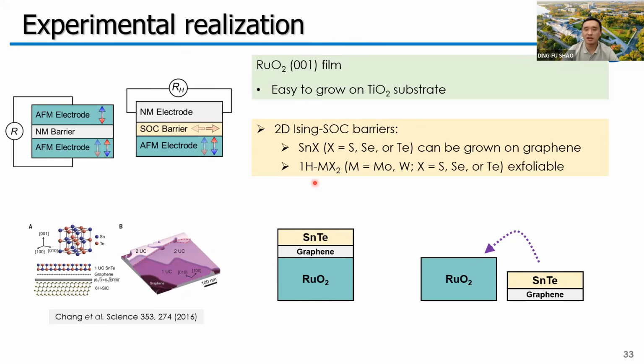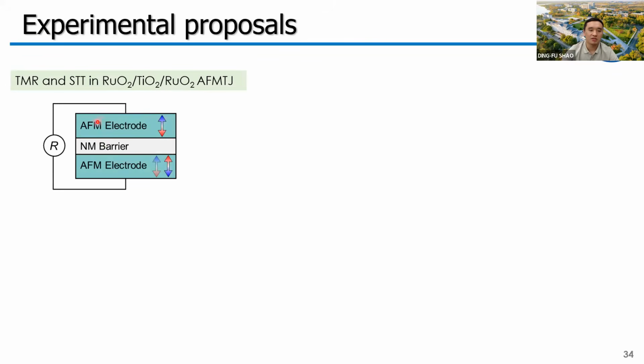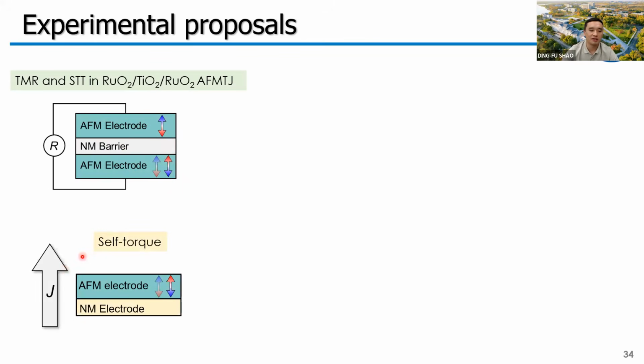Moreover, monolayer MX2 materials such as MoS2 and WSe2 also have Rashba type spin-orbit coupling, so these materials can also be used as a tunneling barrier to observe the tunneling anomalous Hall effect. In this talk, we discussed the STT in the antiferromagnetic tunnel junction with two antiferromagnetic electrode layers. But in fact, we can generate a net spin torque in our device with a single antiferromagnetic layer if the antiferromagnets have a symmetric top and bottom termination.